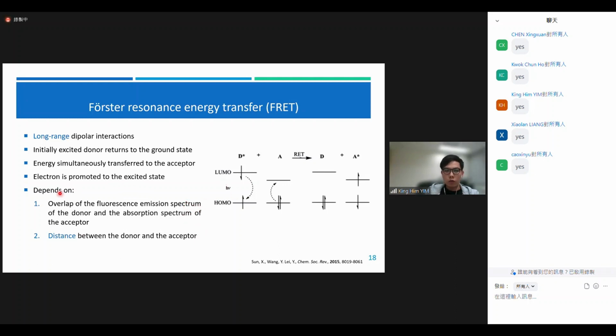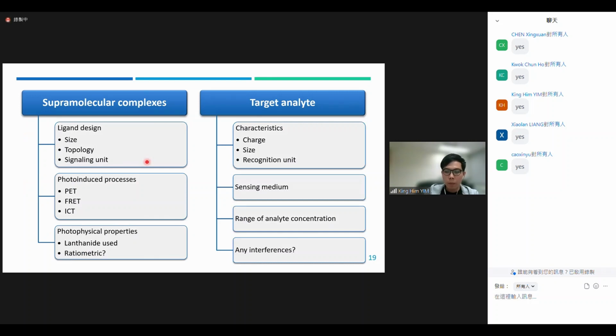When people are preparing a chemosensor, they have to know which energy transfer mechanism applies. One of the very useful criteria is that they have to investigate the fluorescent emission spectrum and absorption spectrum. If there is no overlap between these two spectra, then they can conclude that the energy transfer is not done by FRET. Okay, so here are some of the general energy transfer mechanisms.